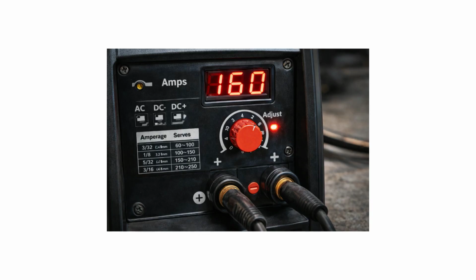Too low amperage causes poor penetration, stubbing, and difficulty maintaining an arc. The electrode sticks to the workpiece frequently. The weld bead will be narrow and poorly shaped with incomplete fusion. Too high amperage causes excessive spatter, electrode overheating, undercutting at the weld edges, and burn through on thin materials.